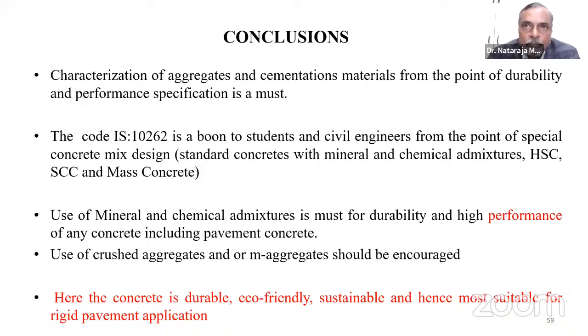There's one more question. The mix design shows superplasticizer as 0.5% of CM. I guess CM is cement, not sure. Would you please elaborate? The content of the plasticizer, my dear friends, is always based on the content of the cement or the content of the cementitious material. You have seen the mix design. In that mix design, I have mentioned the content of the cement, slag, and silica fume, all the three put together.